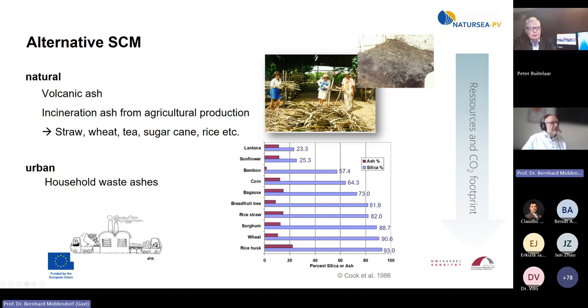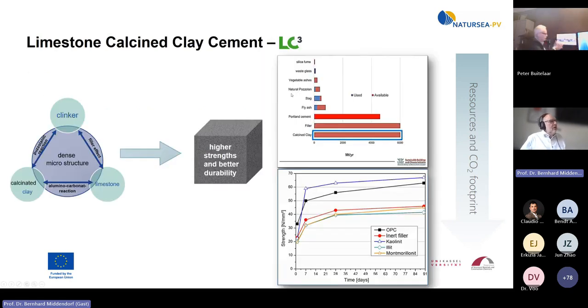Here you see pictures from Cuba where they have the sugar canes, and that is the sugar cane ash, and at one time they had 30 million tons of it. And very famous at the moment, a hot topic, we have limestone calcined clay cement, short LC3. So here in LC3 you have the calcined clay. Here you have the strengths of some different concretes. That is the normal OPC. And here you have concretes with different amounts of clays, and you see that when you use a calcined clay, or we are also working on it, you sometimes get a higher strength than with the normal OPC.